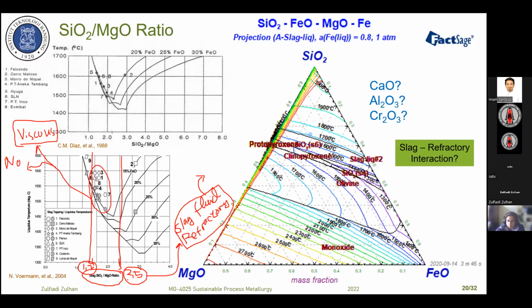And at INCO, at that time in Indonesia, they had 2 kinds of ore. One ore with a high SiO2 to MgO ratio, and the other with a low SiO2 to MgO ratio, and they blended these two kinds of ore in order to get the silica to magnesia ratio we see here. So at the end, they operated the plant with a silica to magnesia ratio close to 2.0; close to here is the silica to magnesia ratio at PT Inco. They mixed the ores after they learned from this situation.